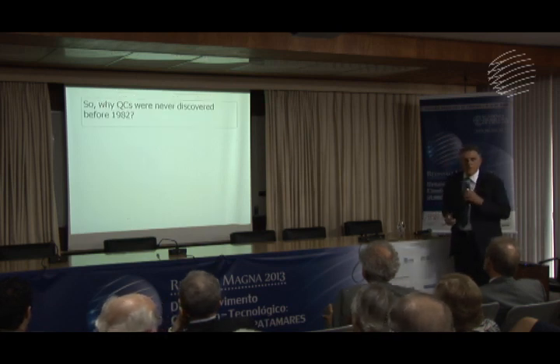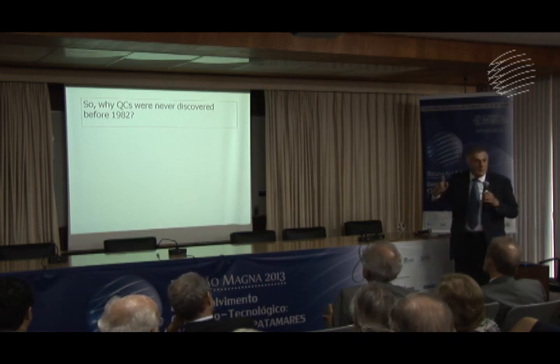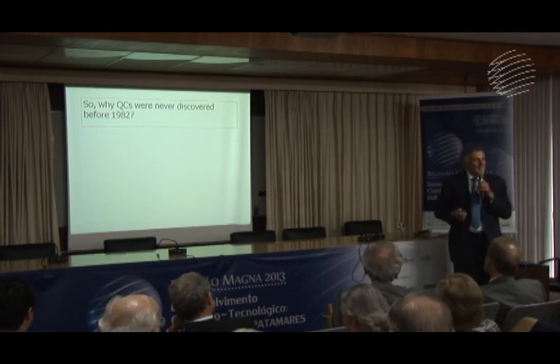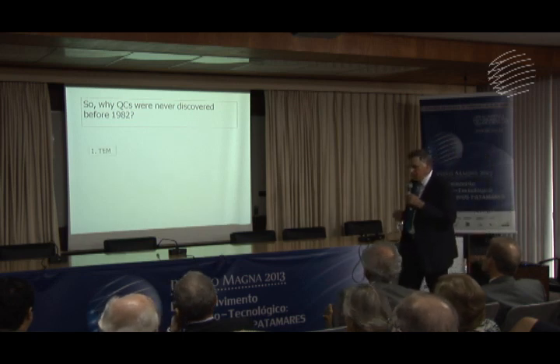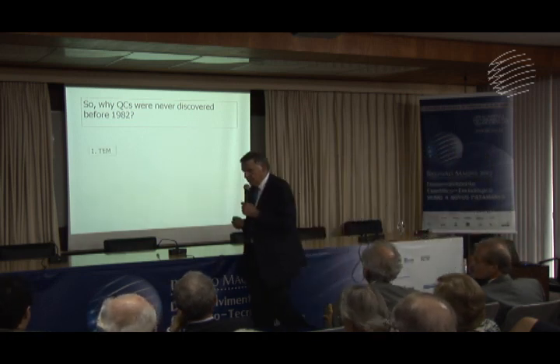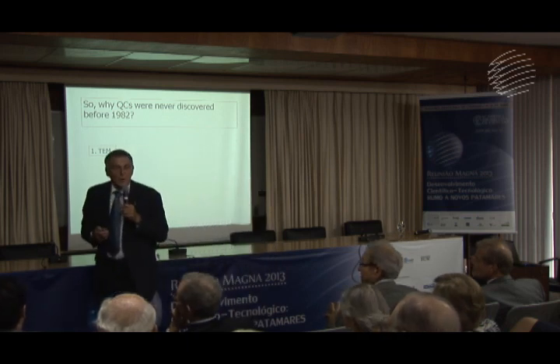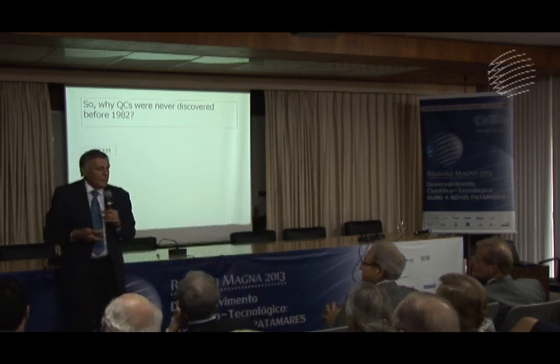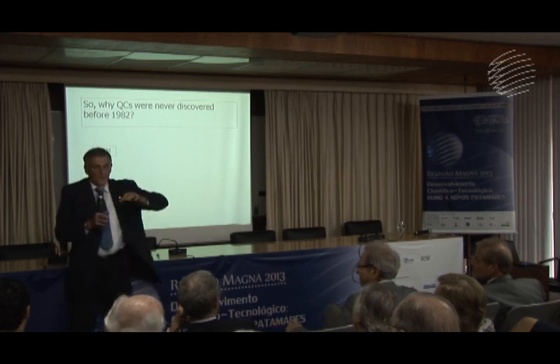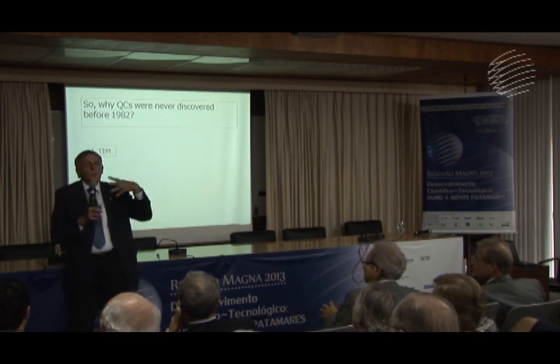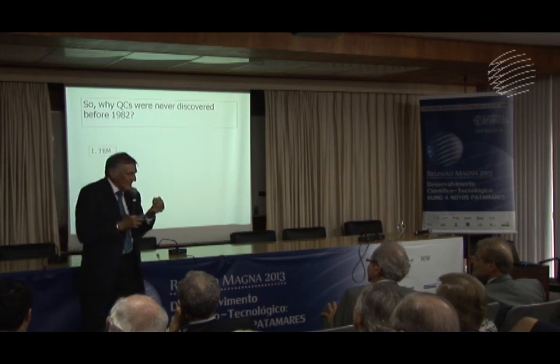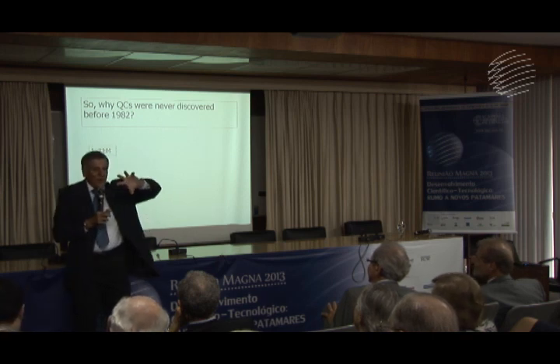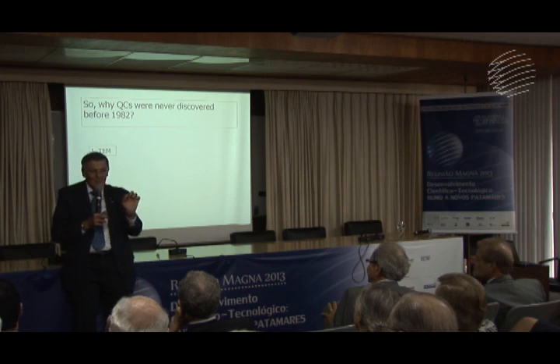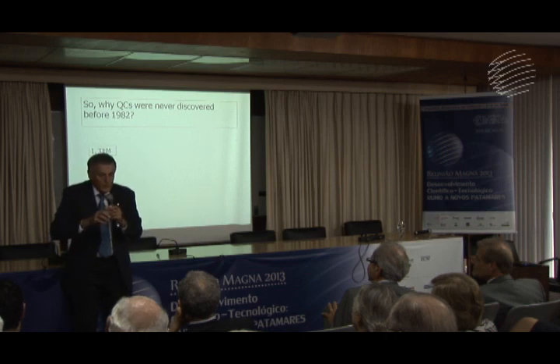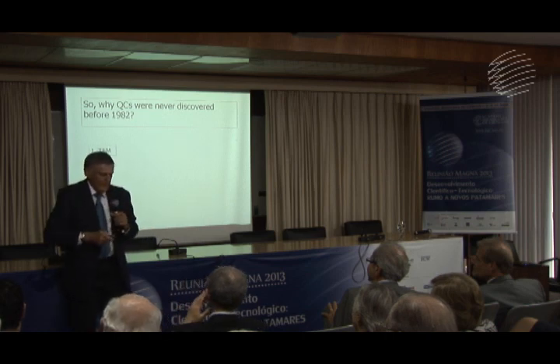So why is it? Now let me give you my answer. From now on, it starts to be subjective. Up to now, it was objective. Number one, TEM. Quasi-periodic crystals had to be discovered by transmission electron microscopy because they were very small. And if you take an X-ray pattern of many small crystals, you lose the rotational symmetry. You do not see the rotational symmetry of one. You get rings instead of spots. So X-ray could not be useful for the discovery. Later on, for accurate measurements, yes, but for the discovery, you need a TEM.